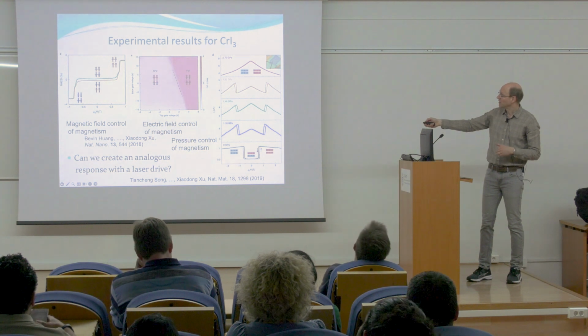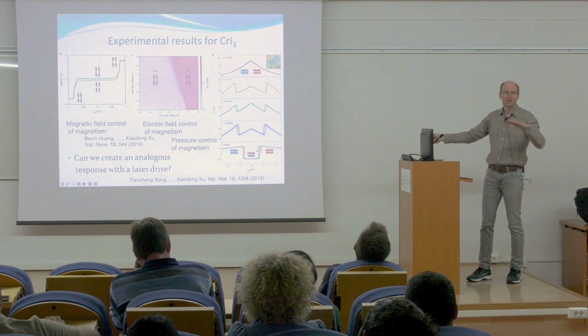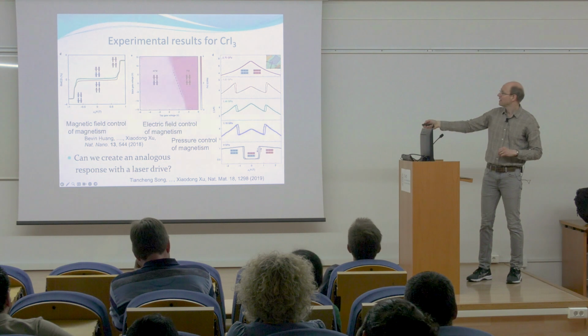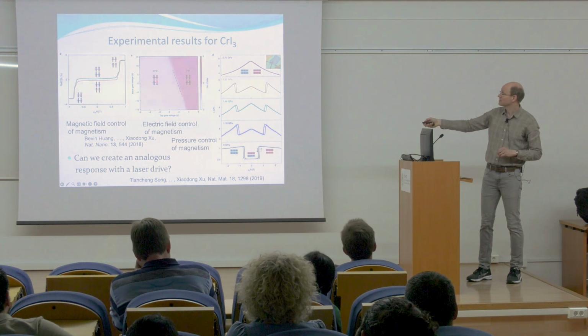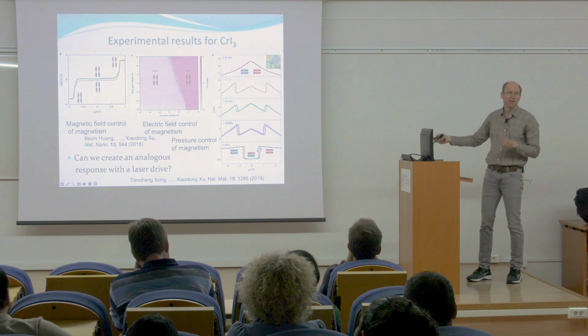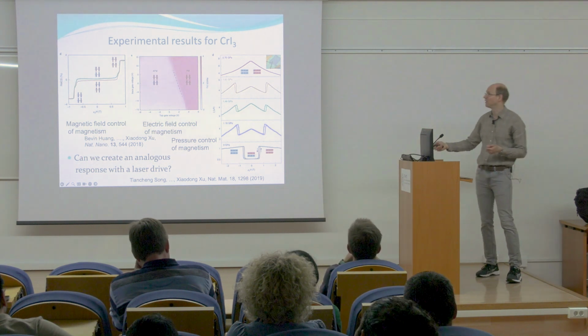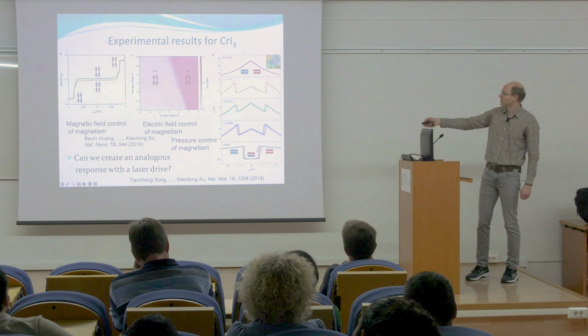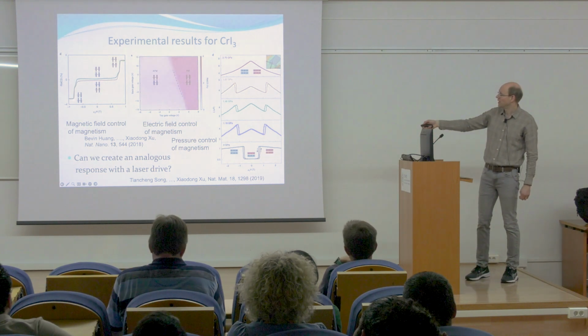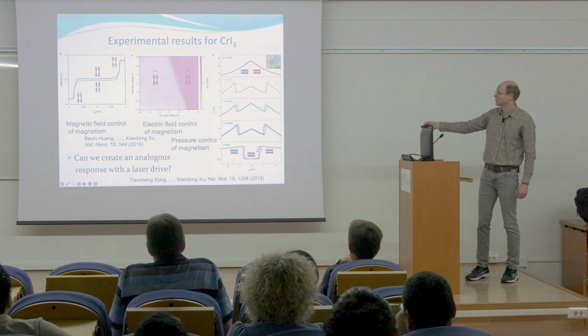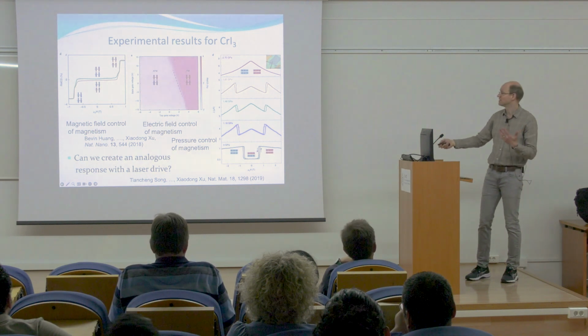So within a layer, the magnetic moments prefer ferromagnetic ordering. However, between the layers, they could be antiferromagnetic or ferromagnetic. For the bilayer system, the equilibrium preference is to be antiferromagnetic. Various experiments have shown that if you apply a magnetic field which is not too large, around 1 Tesla, you can polarize the system.